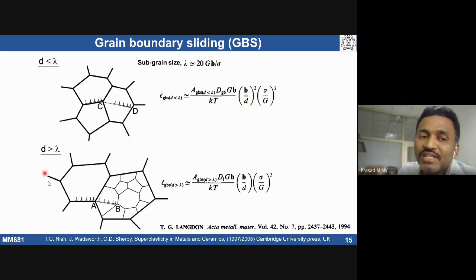If you have coarse grain size, whose size is greater than the subgrain size, then you will have a slightly different constitutive equation for grain boundary sliding, because when you have coarse grains, typically we talk about lattice diffusion. The n value is going to be higher, around 3, so m is going to be 0.33, that is 1 by 3. So this is a kind of typical superplastic behavior.